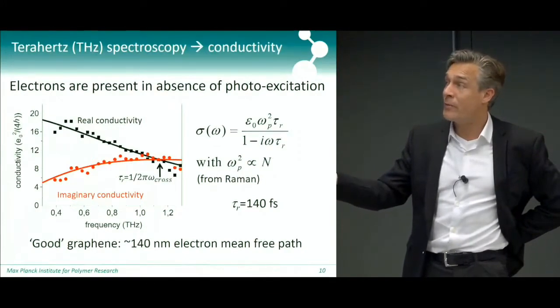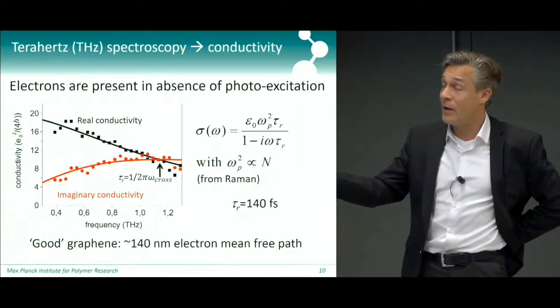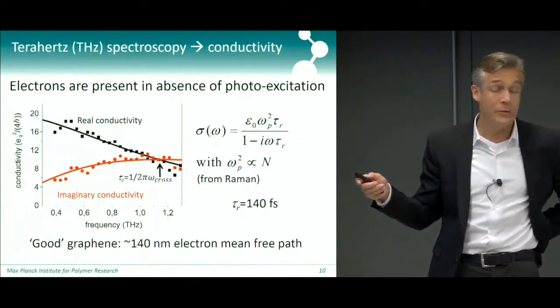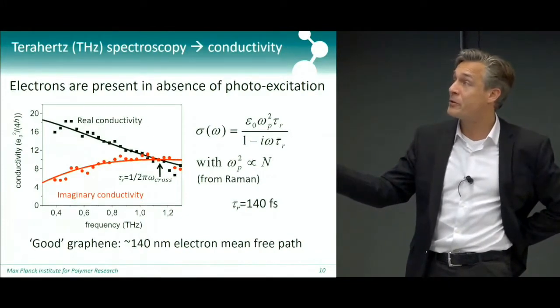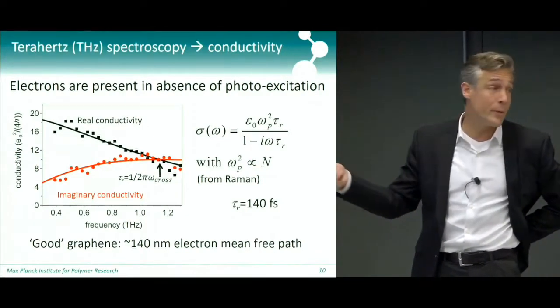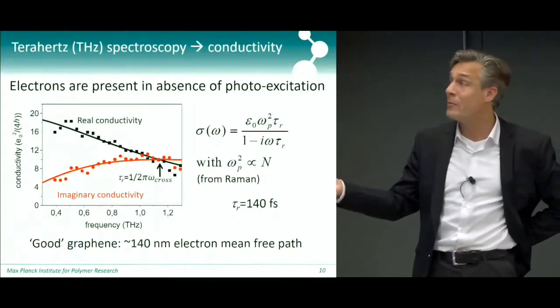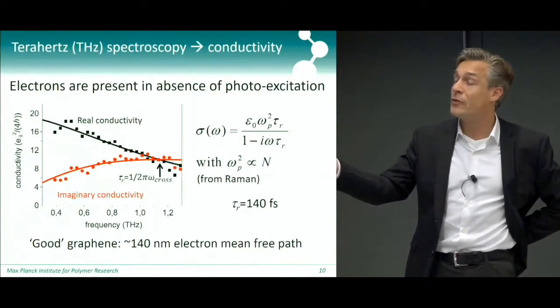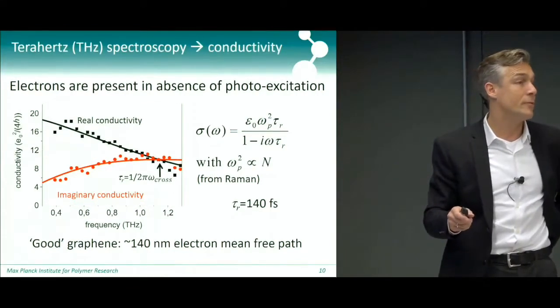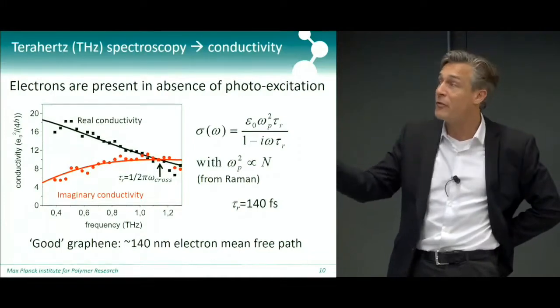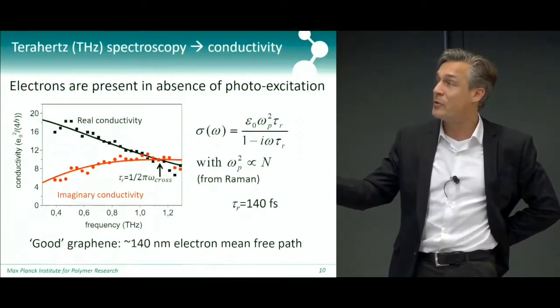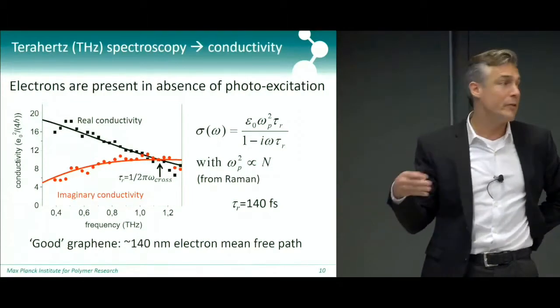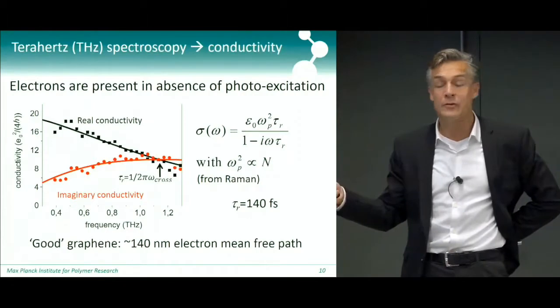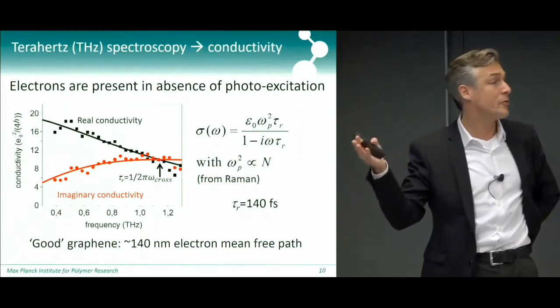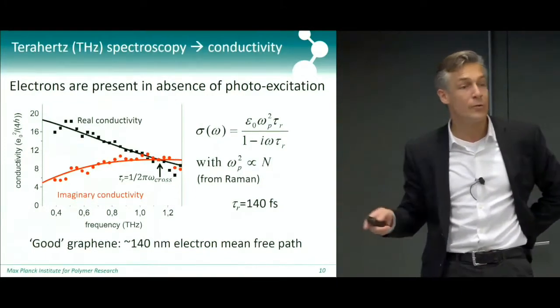That is informative because the lines that you see here are a simple fit to the Drude model, which essentially only has two parameters: the plasma frequency, which is proportional to the number of electrons, a quantity that we can determine independently from Raman measurements, and the curvature and the crossing point of these two lines directly give us the scattering time of the electrons in the graphene. And so for this particular graphene, this is good graphene, the scattering time is 140 femtoseconds, so that's where these two lines cross. And given the Fermi velocity of electrons in this material, that means that the mean free path is about 140 nanometers. So that's all nice and good.